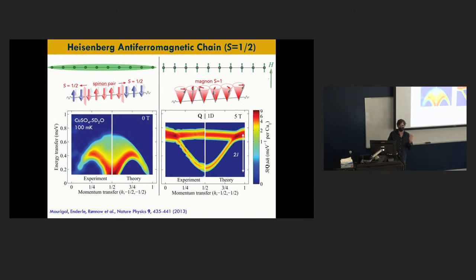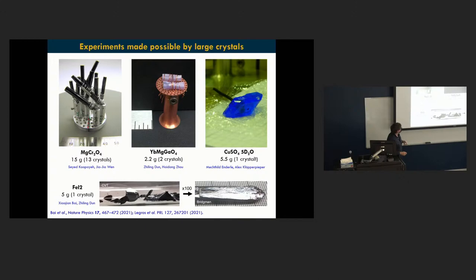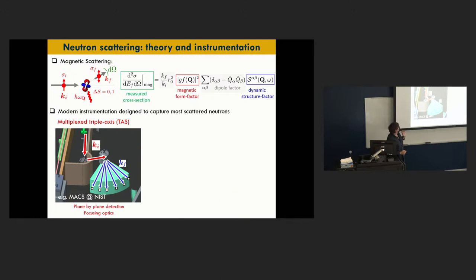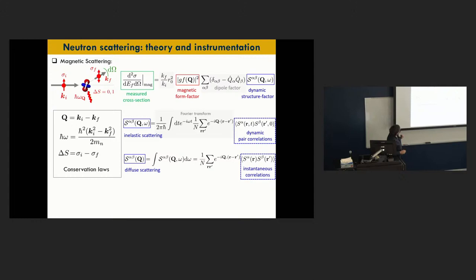Good. So one thing I didn't tell you, and that I kind of hid from this, is that neutron scattering can be a huge pain for a reason, which is that this number here that relates the cross-section to the theory, or to the dynamic structure factor, is extremely small. The neutron scattering cross-section is extremely small. X-rays interact with materials through the electrons, so the scattering is strong. But neutrons interact through a dipole-dipole interaction, so the scattering is very, very weak. And our neutron sources, compared to X-ray scattering sources, are also very weak.